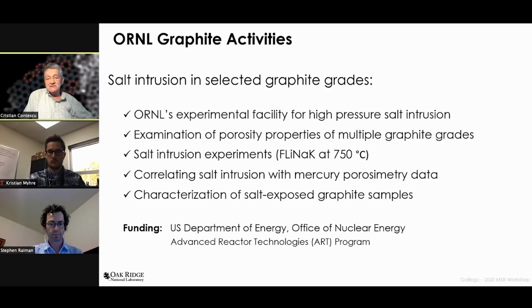So the scientists that worked at ORNL during the MSRE project developed a new grade of graphite with a very low salt intrusion, which is the CGB grade, used for building the prototype of the first reactor that worked. How they did that: they used multiple impregnations of industrial graphite of very high purity, and eventually succeeded in reducing the pore openings down to about 1 micron diameter.